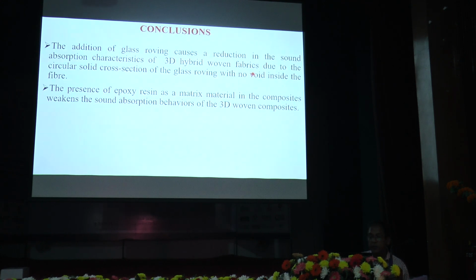Conclusion: the addition of glass roving has caused a reduction in the sound absorption characteristics of 3D hybrid woven fabrics, and the presence of epoxy resin decreases the sound absorption characteristics of the composite.